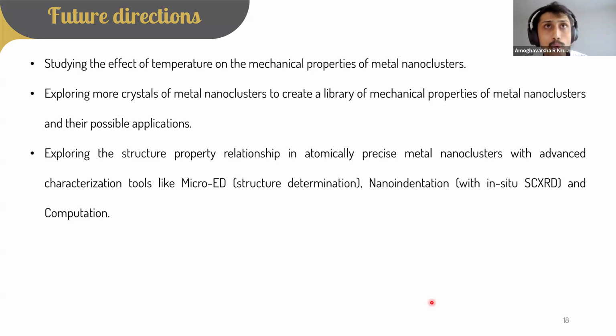It is very powerful to study the solvents which are included within the crystals, and also nano indentation with in situ single crystal XRD. One of the reviewers for this work asked if I can probe the changes in the structure of the nanocluster where we have indented, but that requires a sophisticated instrument which has a single crystal XRD in situ that we don't have. But if we have that, it is very good for our nano indentation studies, and also more computational studies to understand what is happening within the crystal under the stress.